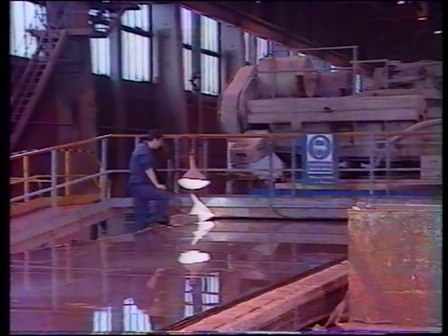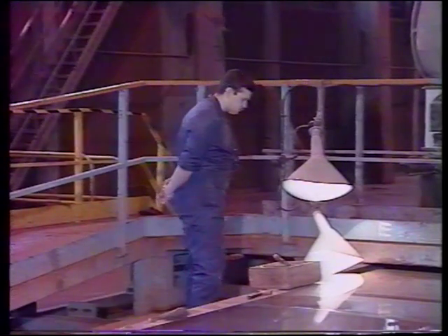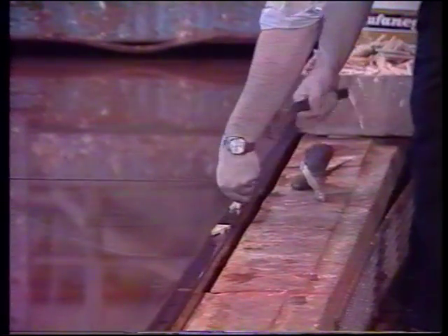It's in the grinding operation that the consistency of glass quality begins to show. Any variations in shape, stress or flatness will quickly show in breakage under the pressure generated by the grinding work on the glass. These effects on the glass can be seen in the trimming bay, the section between the grinders and polishers. Here the operator examines the glass, looking for breakages and surface grinding defects. He then makes sure that all the plates in this position on the line are pegged up properly to prevent any plate movement in the polishing section.